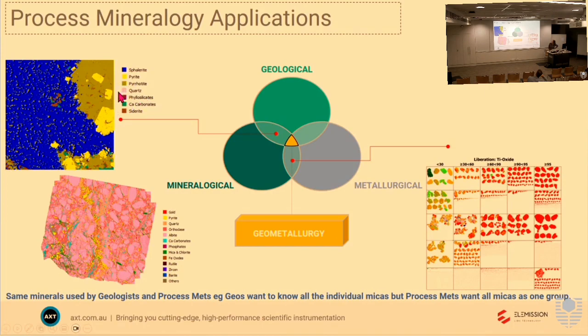So you can see the pyrrhotite here is this sort of greeny browny colour, but there's also finely interspersed pyrrhotite within the sphalerite, and so they would have to grind very, very fine to be able to get that out. To liberate the ore from the gangue as the first pass, it's quite a coarse grind, but to really get the rest of it out is a lot finer grind, and they probably wouldn't end up doing that. They'd probably just sell their concentrate as a lower quality product.